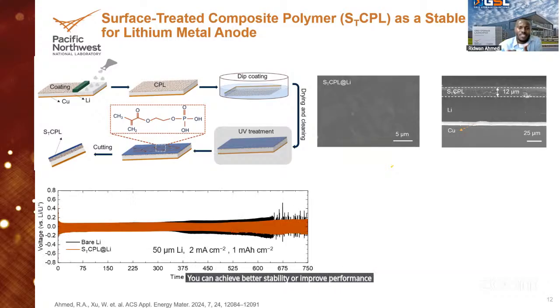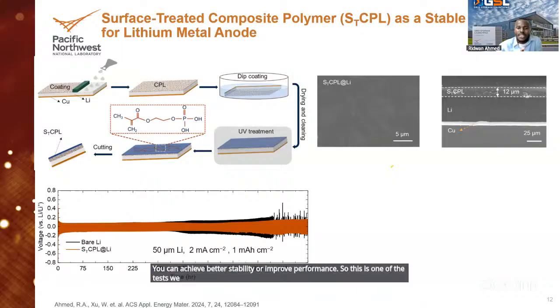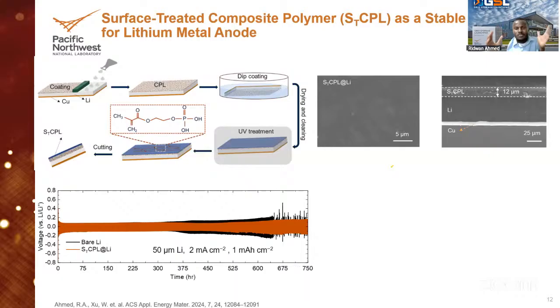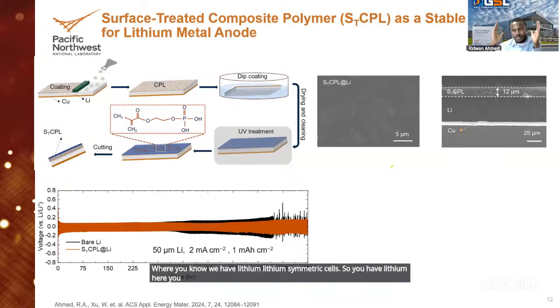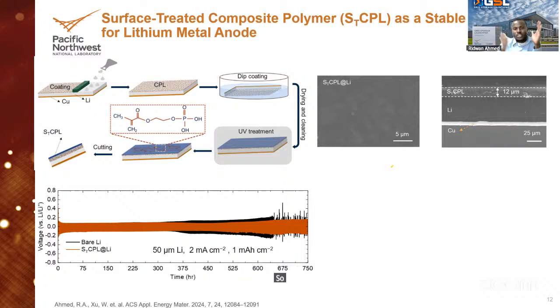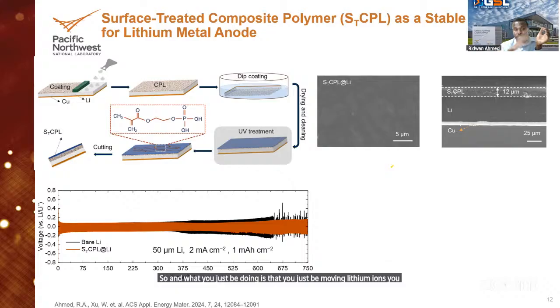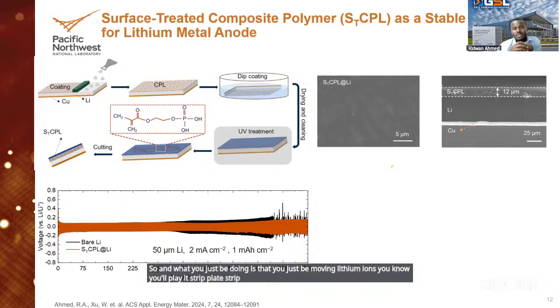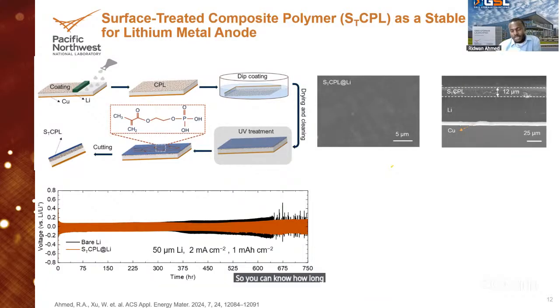So this is one of the tests we usually carry out in the lab, where we have lithium symmetric cells. So you have lithium here, you have lithium here. What you just do is move lithium ions, you plate and strip, and you do it for as long as possible until the cell fails. So you can know the number of cycles it can withstand before it fails.